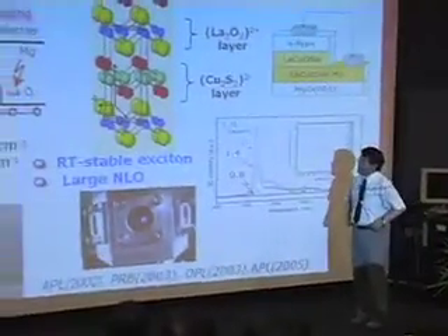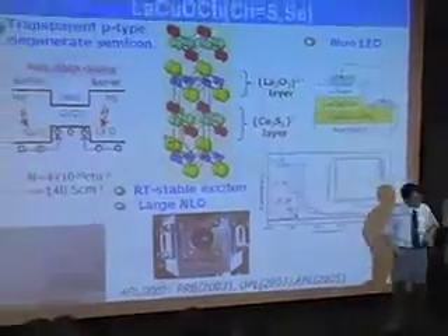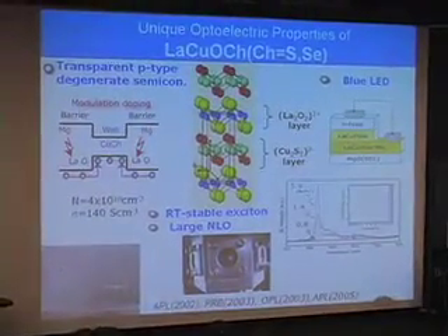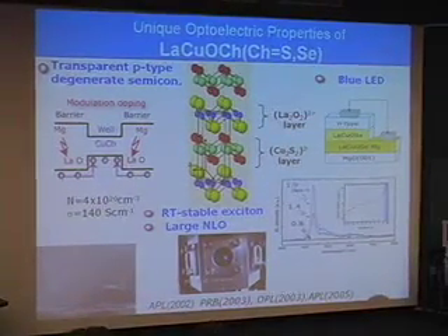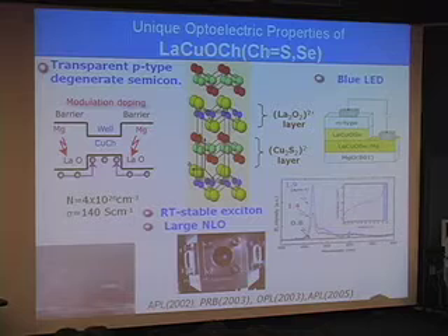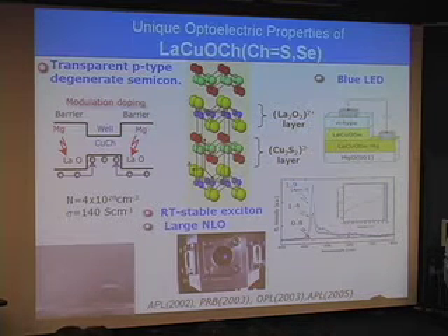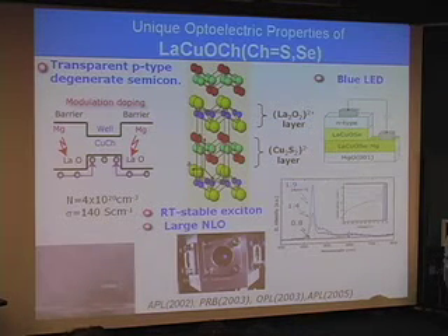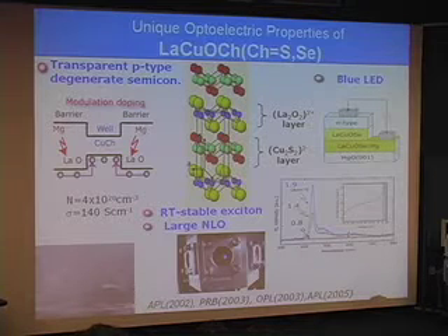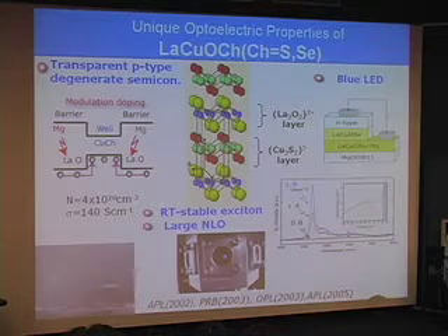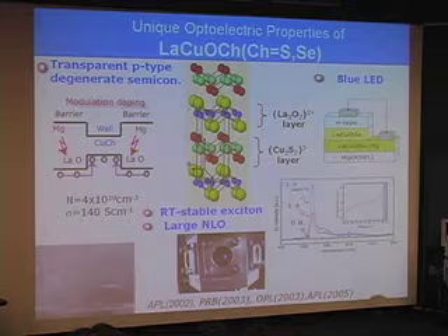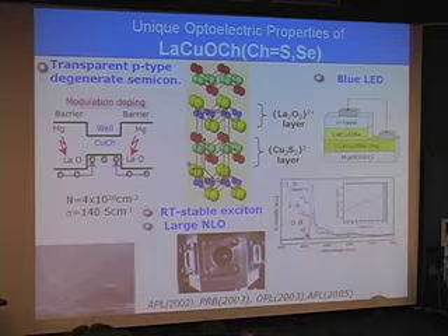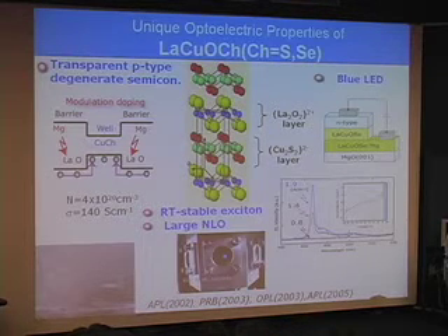I'll show why we discovered this material. It's a very simple story. Our target was a P-type transparent oxide semiconductor, as reported in 1997. Copper aluminum oxide was the first material we reported as a P-type oxide semiconductor, but the performance was not so good. We wanted to improve the property.